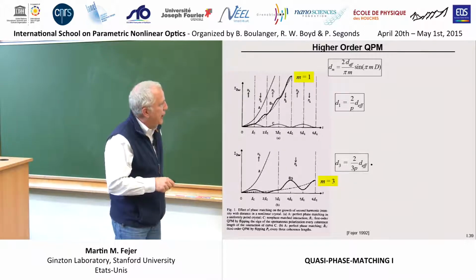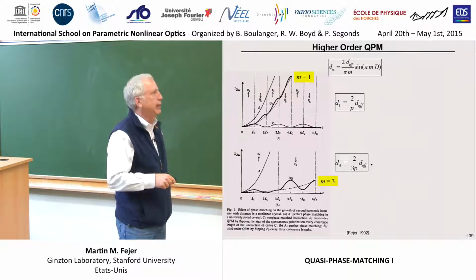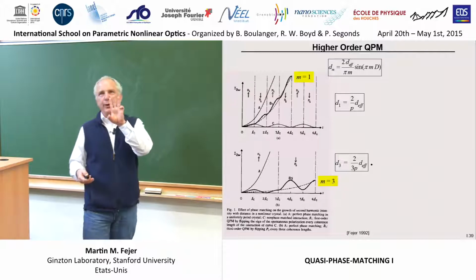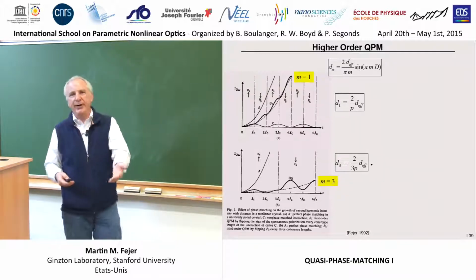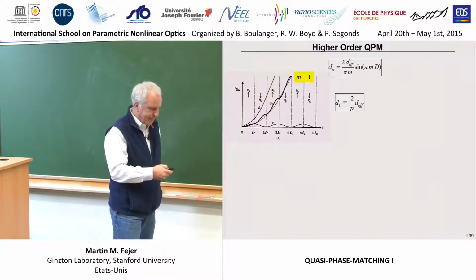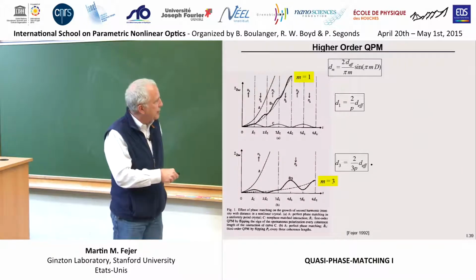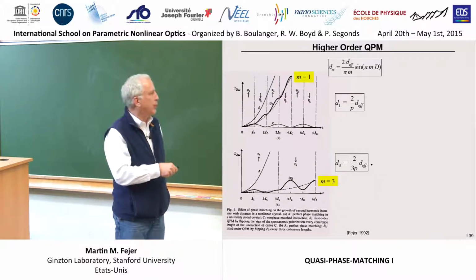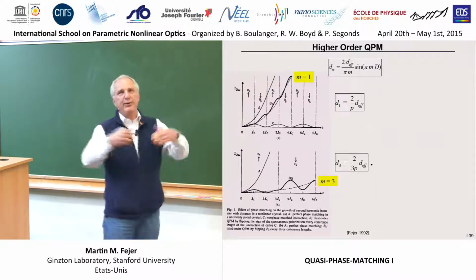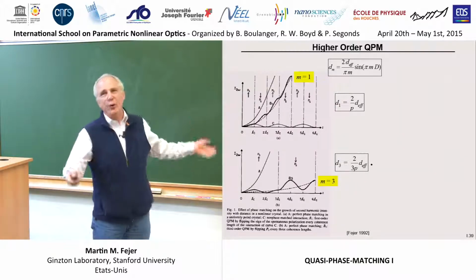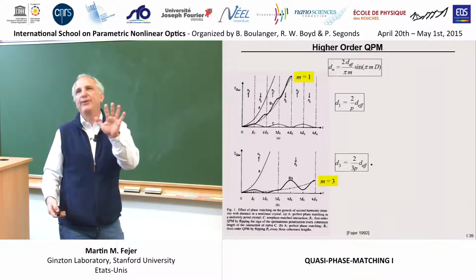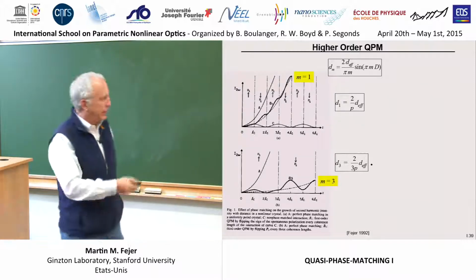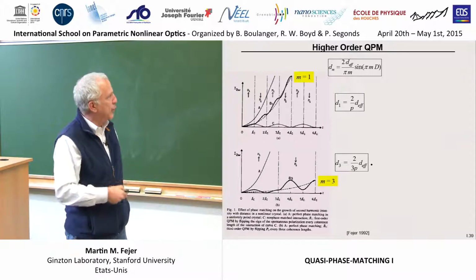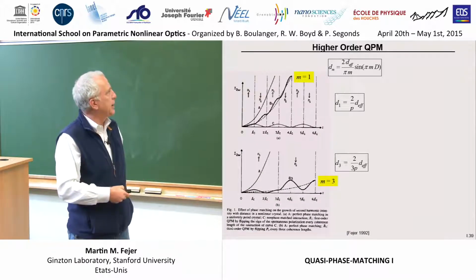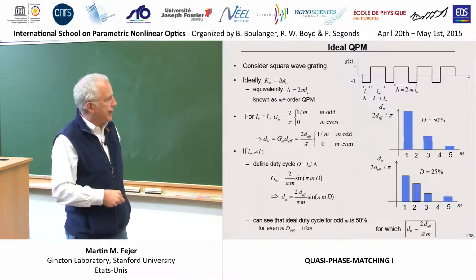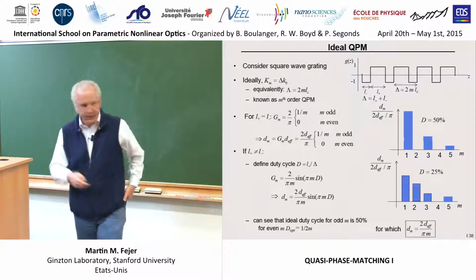You do the same here. You create something, you destroy something, and then you generate 1 coherence length's worth. So that's where the 3 came from, the threefold reduction in the effective nonlinearity. You've just wasted the first 2/3 of each period in this forward and backward process, and you use the last third. If you're doing 5th order quasi-phase matching, you would waste the first 4 and then use the last 1, and you would have 1/5 the effective nonlinear coefficient. So in real space, it's maybe more intuitive than in reciprocal space here. But on the other hand, if you want to do the quantitative calculation for what it is for some oddball case, you can do it.